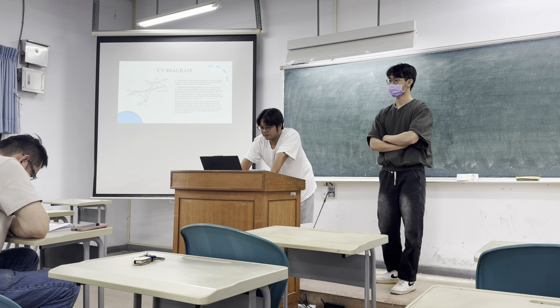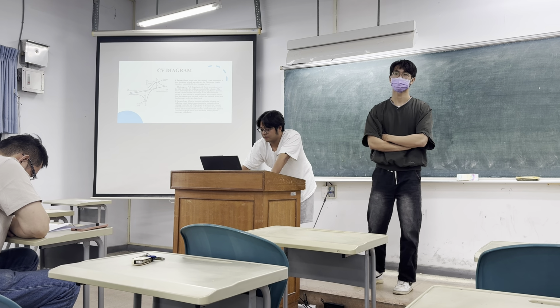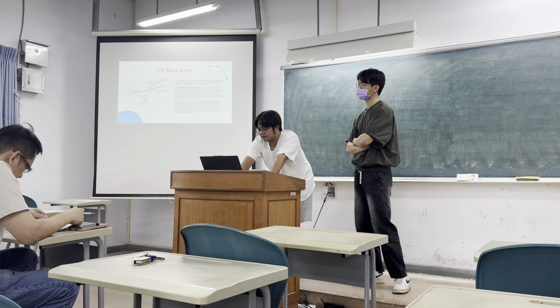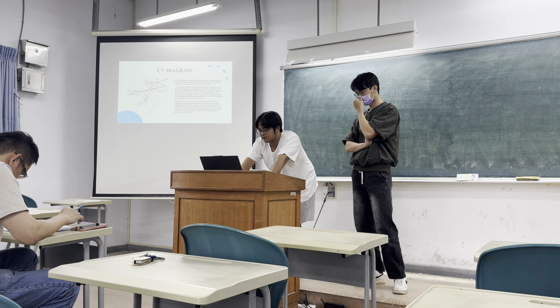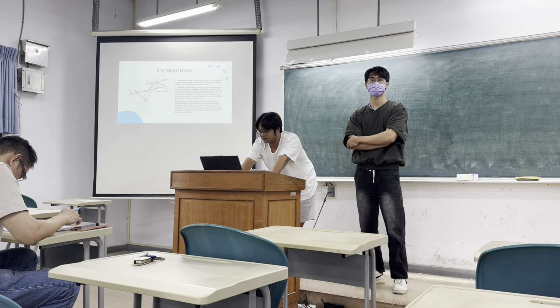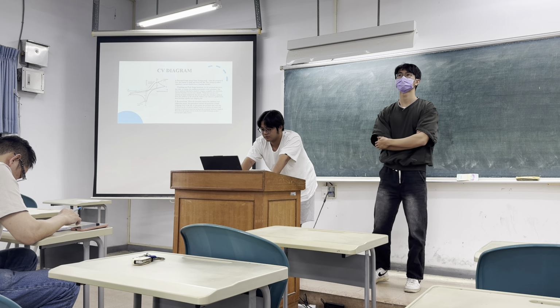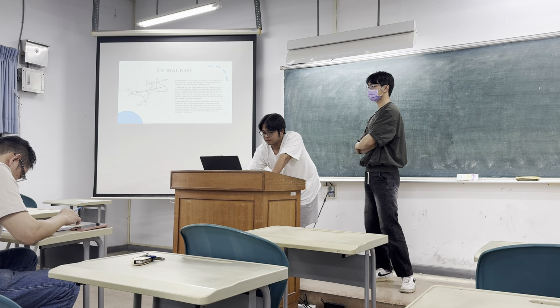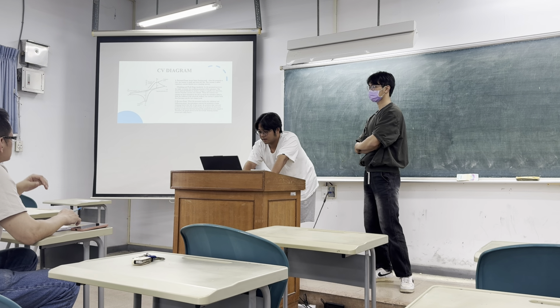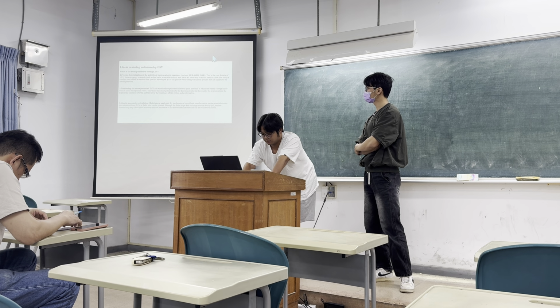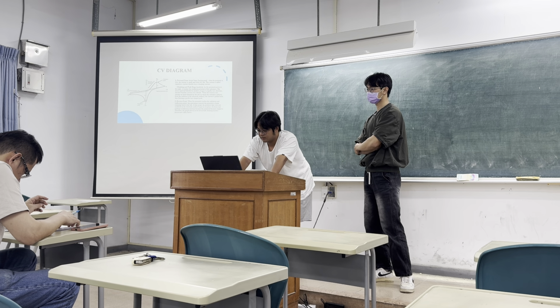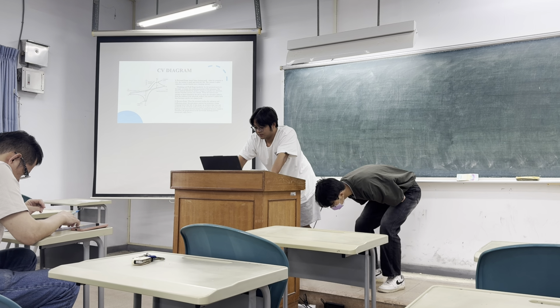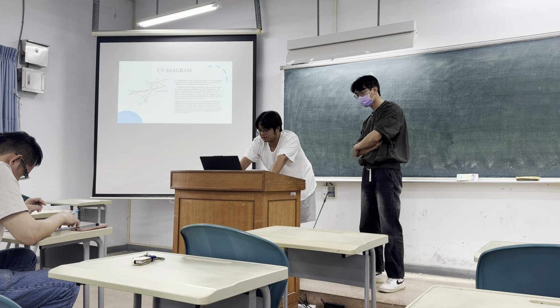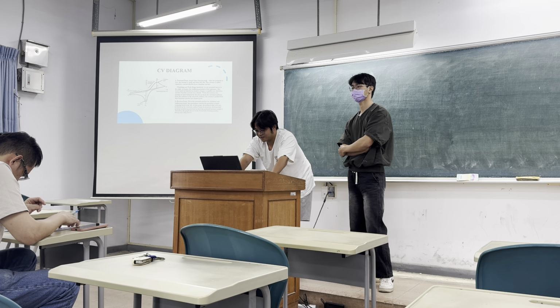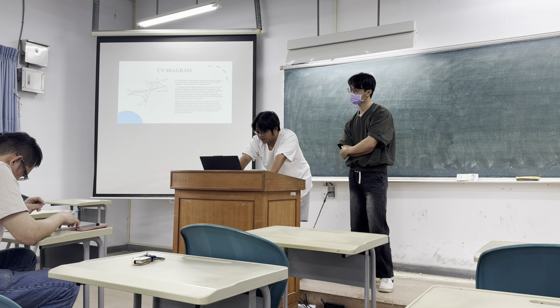When the potential is low, the current is small and relatively flat. At this point, the potential is not yet positive enough, and the active material has not yet begun to undergo chemical reaction. The current is purely a background signal caused by changes in charge arrangement on the electrode surface. And then it climbs to the peak. This is the highest one, the anodic peak. The anodic peak potential has a corresponding peak current. And the lowest point is the cathodic peak potential, and the corresponding current is the cathodic peak.